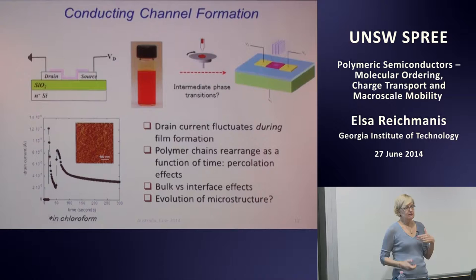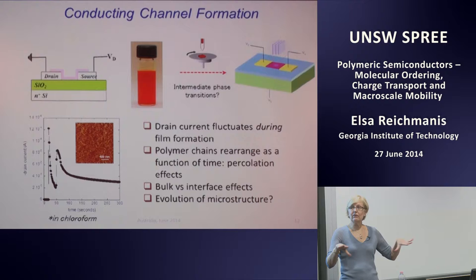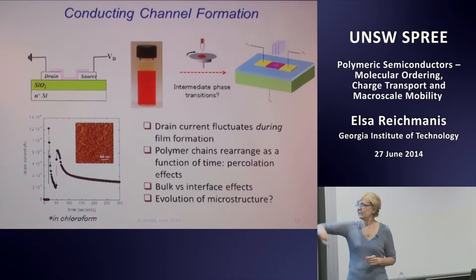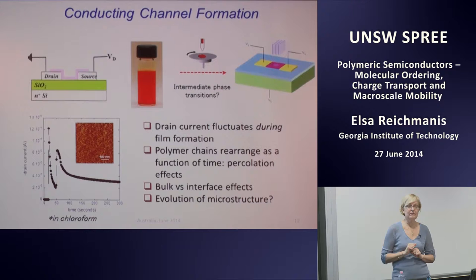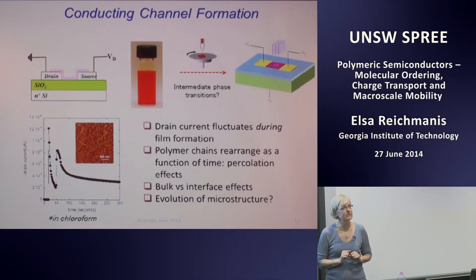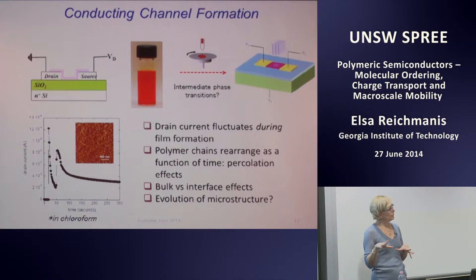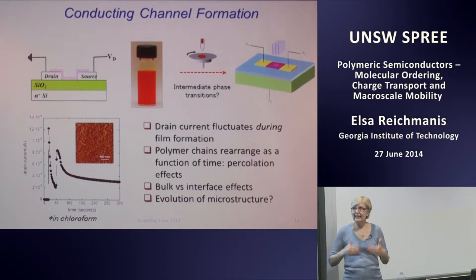All right, if we look at, instead of spin coating, if we just allow the solvent to evaporate from that droplet on the device, and initially use chloroform as a solvent, we notice that the drain current fluctuates during thin film formation. And as a result, what we believe is happening is that the polymer chains rearrange as a function of time, and then we get a percolation network through the film. We get current flowing through the film, and then we can measure a mobility. There are bulk and interface effects in those measurements, and we also don't really know what's happening to the microstructure of the film as that microstructure is forming.